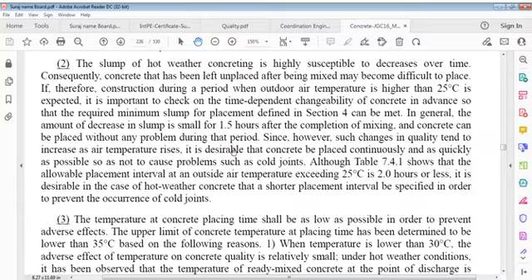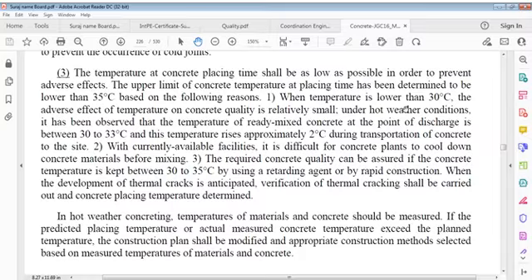Since such changes in quality tend to increase as air temperature rises, it is desirable that concrete be placed continuously and as quickly as possible so as not to cause problems such as cold joints. The table shows that allowable placement interval at an outside air temperature exceeding 25 degrees Celsius is 2 hours or less. It is desirable in case of hot weather concrete that shorter placement interval be specified in order to prevent occurrence of cold joints. Temperature of concrete at placing time shall be as low as possible in order to prevent adverse effects.